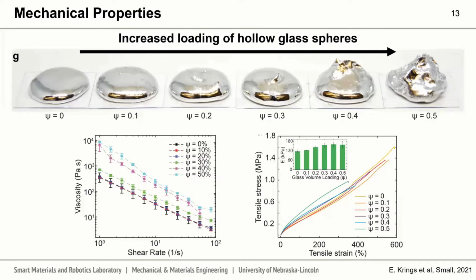Importantly, as the loading of this low density phase is increased into the liquid metal from 0 on the left to 50% by volume on the right, we see a change in its moldability, which shows up as a change in viscosity of the filler. However, we see negligible changes as we begin to look at the stiffness or modulus of the composite at 50% by volume of this multi-phase filler in the composite.